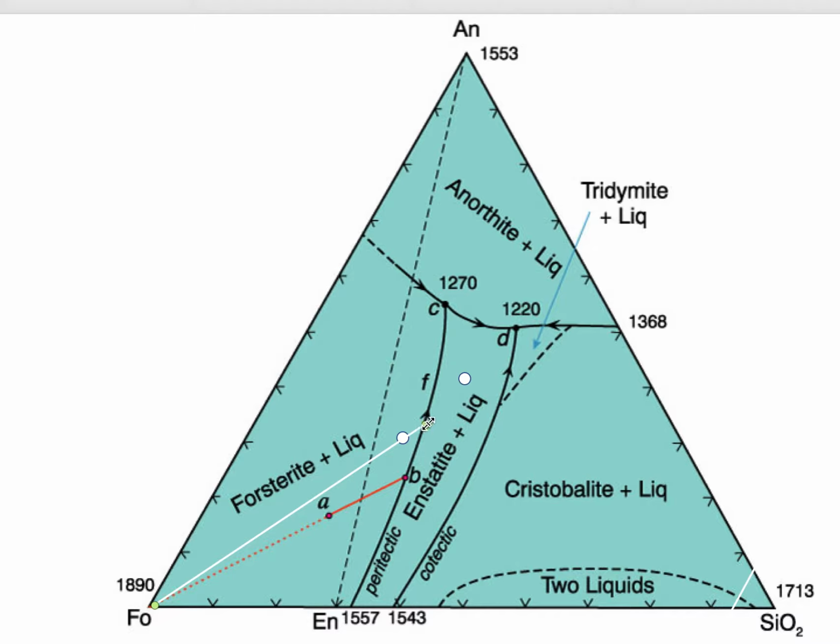The liquid, when it reaches this point, will begin precipitating enstatite, and as it does so, the silica-rich liquid will begin reacting with the forsterite and consuming it. Now, when will the forsterite be completely consumed? Well, the liquid will travel down this peritectic curve where it will eventually reach 1270 degrees centigrade, and that is the point at which forsterite will no longer be present. The liquid will sit there at a constant temperature of 1270 degrees, reacting until there's no forsterite left.